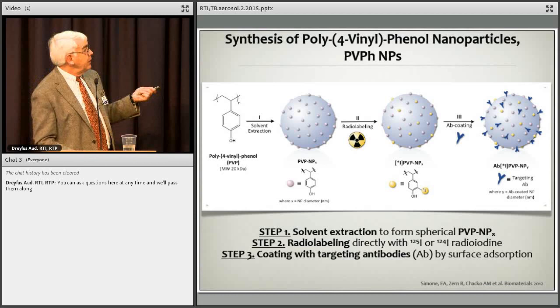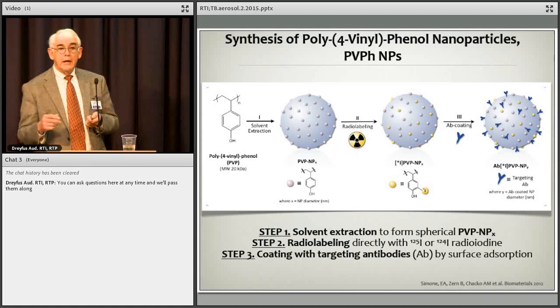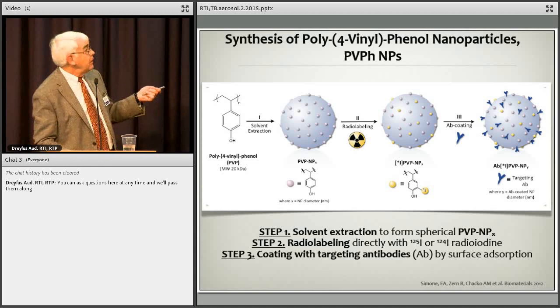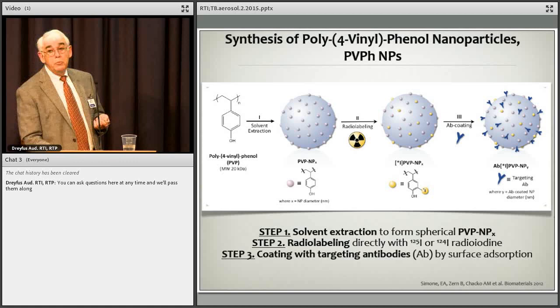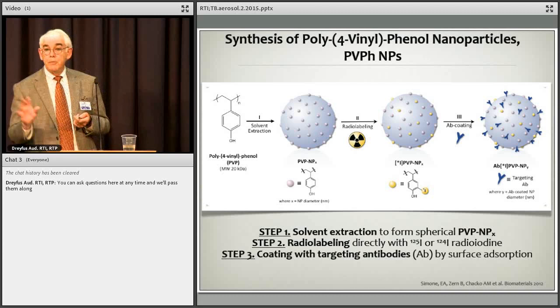Normally, it's done on tyrosine on antibodies, and you put it through this oxidation reaction, and you put an iodine on here adjacent to the hydroxyl, and the iodine is the radioactive agent, and that does PET imaging. Well, we were talking to the group at UPenn, and we said, well, there are actually polymers used as photoresists that would have this structure, and I bet we could make them into particles, and then we could do the iodination reaction just as you do now, so we're not changing your setup at all for doing iodination.